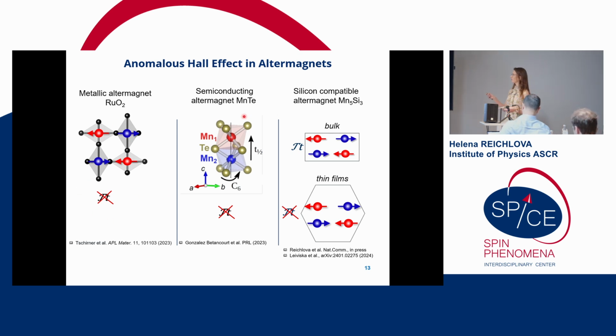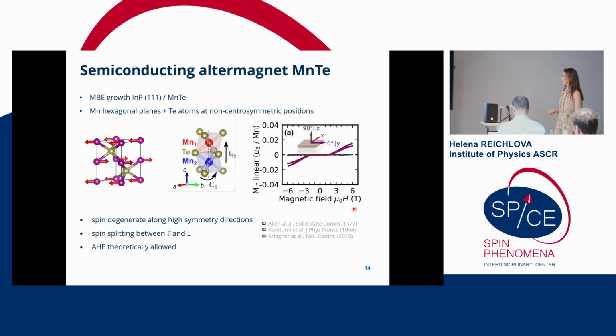However, we have also two other candidates which from an experimental perspective we tend to like even more, because, unlike in ruthenium dioxide, where the Néel vector in zero magnetic field is just in the orientation where it does not allow for the anomalous Hall effect, in these two materials, already in zero magnetic field, we can have the anomalous Hall effect, and therefore we can observe a spontaneous signal. So these are two materials, and let me start with manganese telluride.